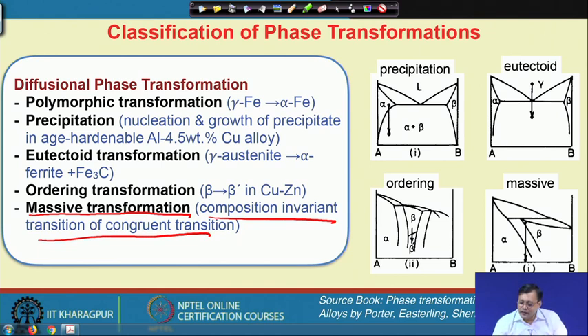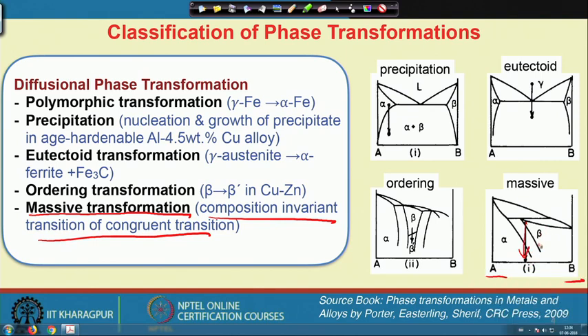One example of such a massive transformation is shown here. If we have such a peritectic type of transformation, where from beta we will get actually alpha. However, please take note that there is no Martensitic like transformation involved in this process. This is a complete diffusional phase transition from beta to alpha. So, this is called a massive transformation which involves diffusional movement of the atoms.